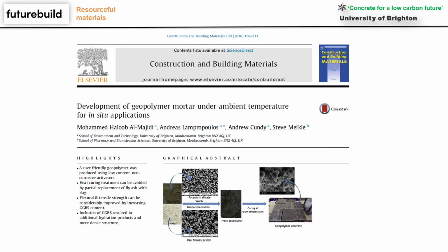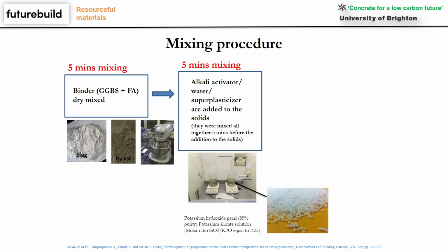So most of the materials we are using so far are materials that use quite a lot of fly ash, and actually we need to have heat curing, and we can get a very good strength in one day. This is fantastic for precast applications. What we're focusing on now is a material which gives quite good characteristics for in situ casting as well, and is a user-friendly, non-corrosive material. So we used a combination of GGBS and fly ash.